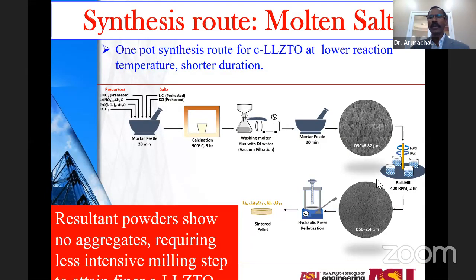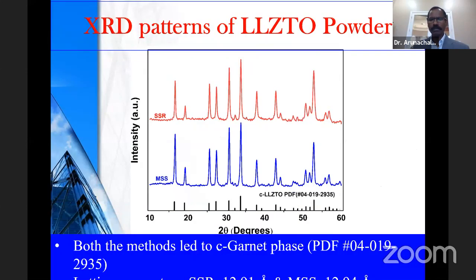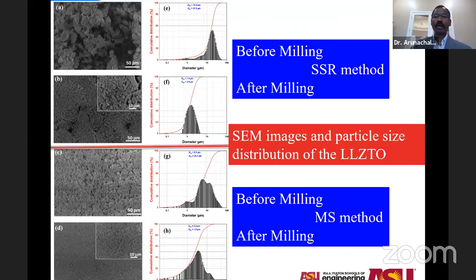Once that is done, you have relatively smaller particles, and then you can have a very quick or shorter milling process to get relatively finer powder and make pellets. Once you sinter, the pellets always turn out semi-transparent, with an extremely high density and non-porous structure. After ensuring that the pellets have a stable cubic structure, obviously both the methods, solid-state reaction and the molten salt method, led to the cubic garnet phase.